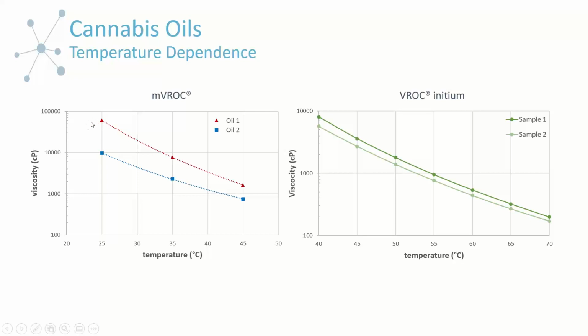So in this case, for one of these oils, we're approaching almost 100,000 centipoise at something close to room temperature. And I think the highest one we've ever measured, although I don't have that data presented here, was about 300,000 centipoise. So these can get very high viscosity, and as I stated, there is a significant temperature dependence. Although we don't have true model fits to these, they tend to follow either an Arrhenius or modified Arrhenius law, which can allow you to do some extrapolation. But you can see the temperature sensitivity, and you can see how high in viscosity these can get as we approach room temperature. And then you can imagine if you get to colder temperatures, as I said, they're concerned about extreme usage environments. So if you get to much colder temperatures, these would be extremely high viscosity.